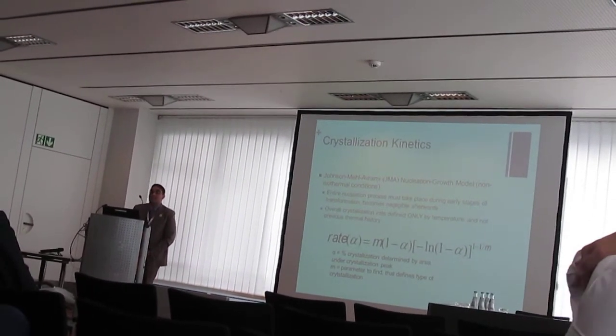So finally we got to the crystallization kinetics of our 2 bioglass. To determine the crystallization kinetics, we use the JMA model for nucleation growth for non-isothermal conditions.